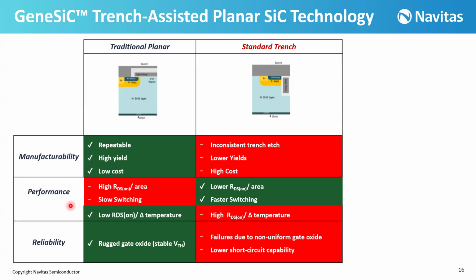In the performance, obviously, trench devices have lower R-on-SP or lower RDS-on at the same active area. As I mentioned, we have higher channel mobility, and also the cell pitches are smaller, and also faster switching because of the lower CGD here. But another performance comparison is the temperature coefficient. Normally, we have a lower temperature coefficient for the planar compared to the trench. And finally, in the reliability, as I mentioned and explained, in the trench we have a higher electric field at the gate oxide, and it causes lower reliability, lower short circuit capability, and failures due to non-uniform gate oxide.